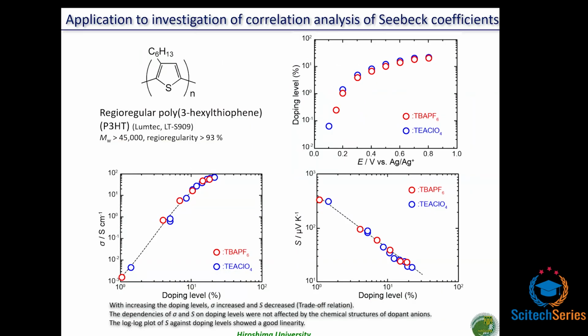Electrical conductivity linearly increased with increasing the doping levels, and finally saturated at around 20% of doping levels. On the other hand, Seebeck coefficient decreased with increasing the doping level. This phenomenon is a typical trade-off relationship that can also be observed in inorganic thermoelectric materials. It was found that the dependencies of these factors on doping levels were not affected by the chemical structure of the dopant ions. Interestingly, it was found that the log plot of Seebeck coefficient against doping levels showed a good linearity.